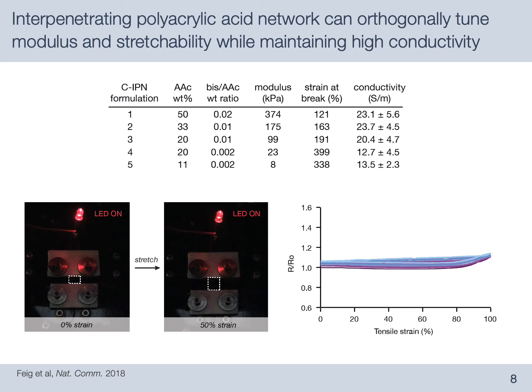Moreover, because the conductive component is formed into a macroscopically connected network, and because there is plenty of free volume in the hydrogel to accommodate strain, our CIPN can maintain conductivity even when stretching to 100% strain over 10 cycles, as shown on the bottom right.